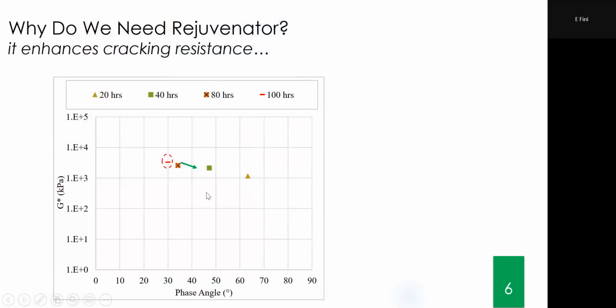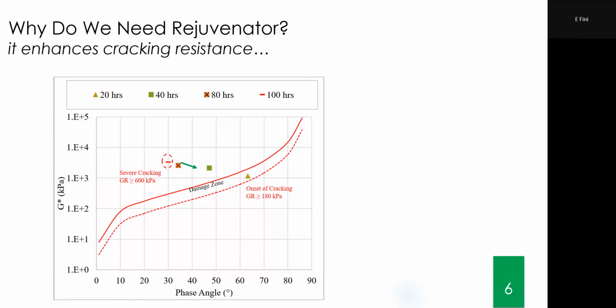So if my rejuvenator is going to work, it's supposed to reverse it. Let's see what it does. In this test, we have a measure developed by Glover-Rowe, which looks at cracking resistance. If the sample is above this red solid line, it's supposed to be prone to crack. We call it severe cracking.